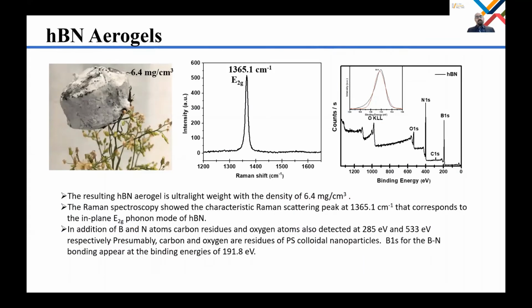The resulting BN aerogel is ultra lightweight with a density of 6.4 milligram per cubic centimeter. Here we use Raman spectroscopy to determine the bonding characteristic and phase purity of the BN aerogel. Raman spectroscopy shows the characteristic E2g phonon mode of BN. In addition to Raman spectroscopy, we used XPS analysis to quantify the chemical composition of the BN aerogel. In the XPS characterization, in addition to the boron and nitrogen atoms, we observed carbon and oxygen atoms. These are most probably coming from the polystyrene nanoparticle residues after burning out the polystyrene.